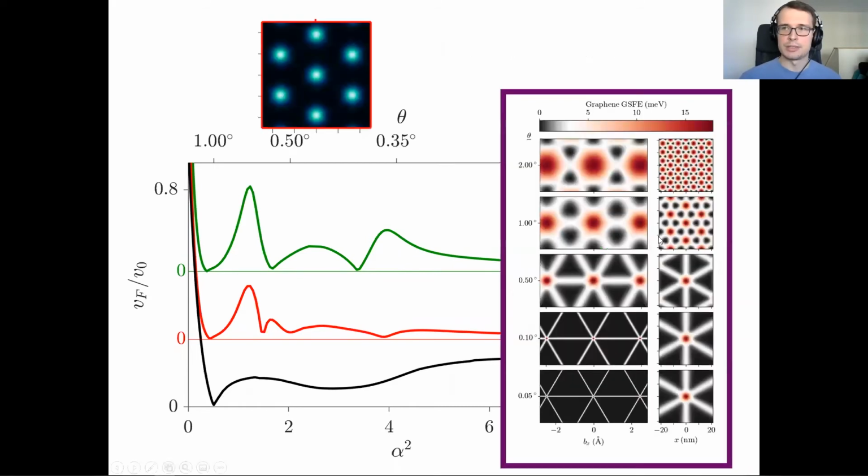And the reason for that is the atomic relaxation. At small angles, you're no longer able to create a smooth Moiré potential. Instead, the local structure of these AA spots becomes fixed, so the potential well is always the same shape. So you're not able to tune this harmonic oscillator like Dirac cone state any smaller because you're not able to make the well any bigger than this size. If you try to make it bigger, the atomic relaxations will push it and compress it into this nodal structure.